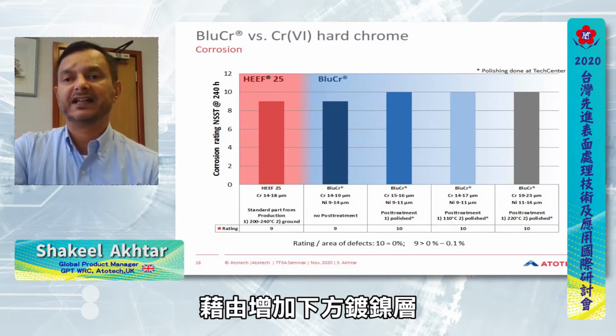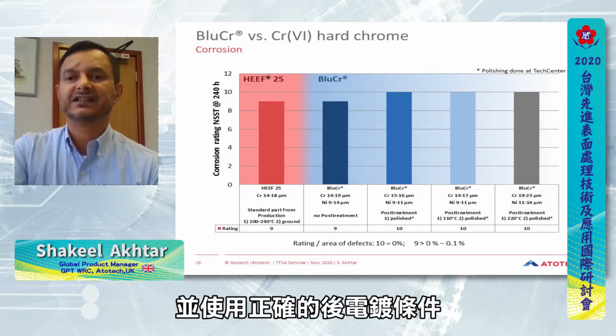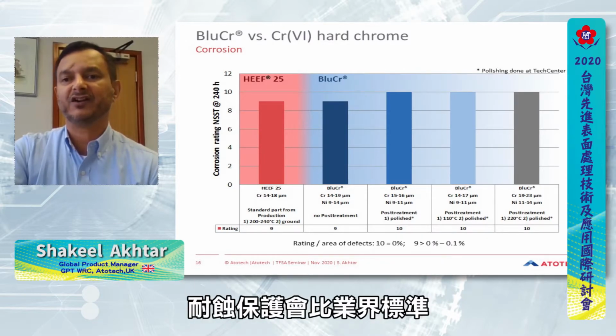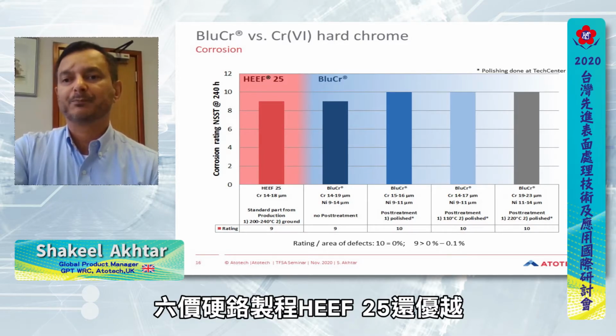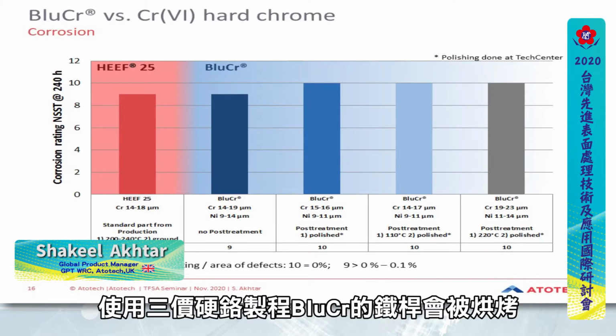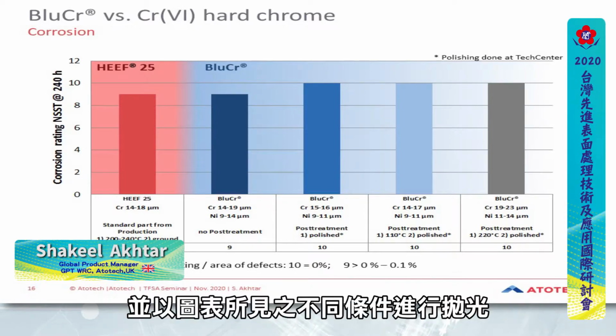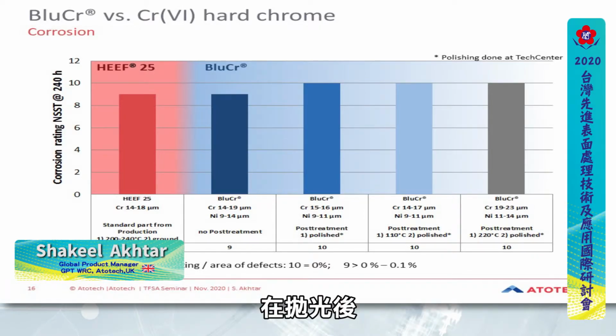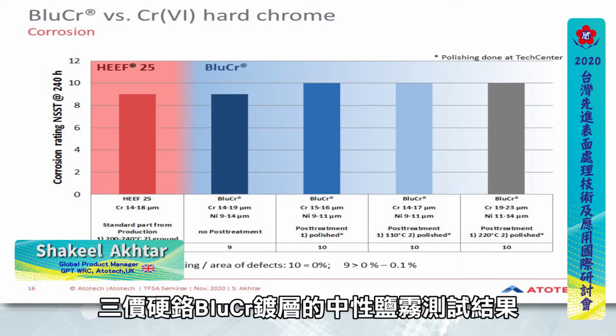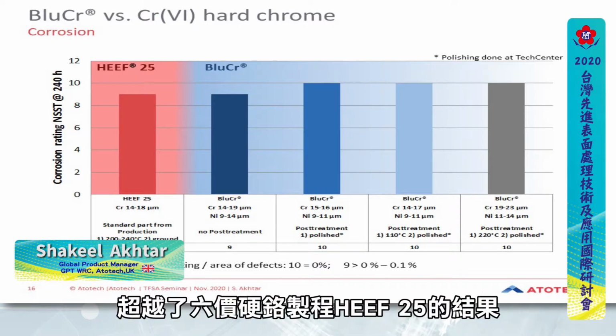With the nickel underlayer, the chrome protection is superior to the industry standard hexavalent process HEEF 25 when the correct post-treatment conditions are used. In this graph, rods plated in BluCr were baked and polished with different conditions, as can be seen. After polishing, the neutral salt spray results for BluCr exceed HEEF 25.